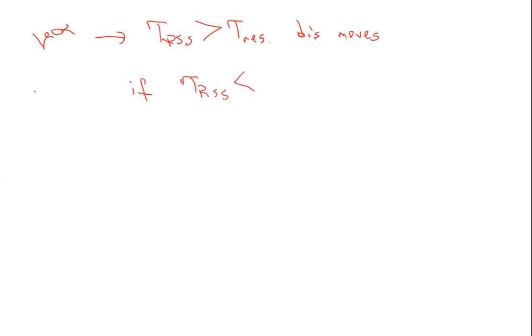Velocity of dislocation, all right. Once the resolved shear stress is greater than the lattice resistance, right? We have dislocation movement. Dislocation moves. If vice versa, resolved shear stress is less than the lattice resistance, we don't have any velocity. But if it is greater than the lattice resistance, which is very low for FCC, maybe 5 megapascal, 10 megapascal, maybe 40 megapascal, depending on the FCC material, we have velocity.